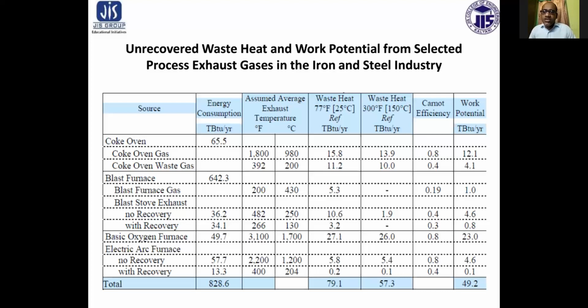Now, for the basic oxygen furnace also, there is a work potential of about 23 trillion BTU per year. For the electric arc furnace, with recovery, it is only 0.1 trillion BTU per year, but with no recovery it is 4.6 trillion BTU per year. So as a whole total, with recovery and with no recovery, if we can recover all this energy, the total work potential is 49.2 trillion BTU per year of energy we can save, with respect to a total energy consumption of 828.6 trillion BTU per year.